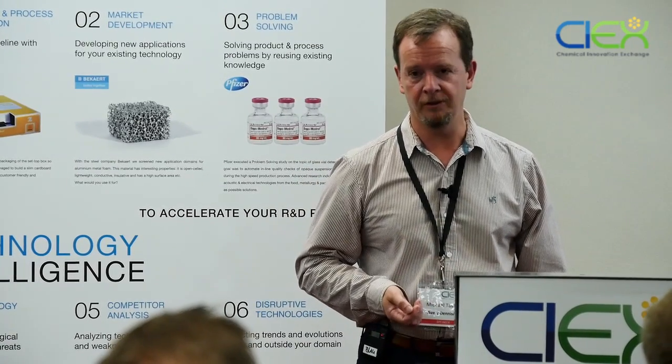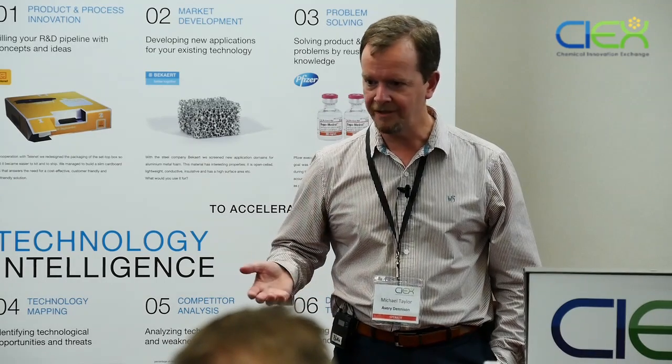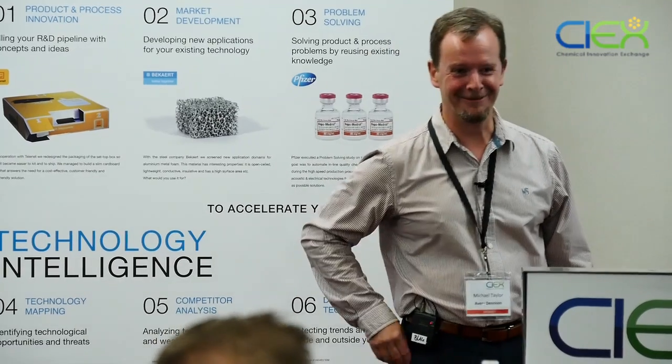I mean, of course, that's why we do all this testing. We have massive claims if we have something like that going on. I've got a Reebok shirt that I paid a fortune for, and it's got a huge ghosting patch here from the adhesive. At Avery Dennison, we try our damnedest. We go through rigorous testing to make sure that doesn't happen. So it's a tough requirement, because what we're not in control of is suddenly the garment changes or the fabric changes, a new coating is put on it. And one week it's working, the next week it's not. The adhesive is not just about the adhesive, it's about the surface that it's sitting on as well. And if that changes, then you're in trouble and you have to go through all this testing again. But yeah, if you're really stuck, N-heptane. I carry a bottle around with me all the time.